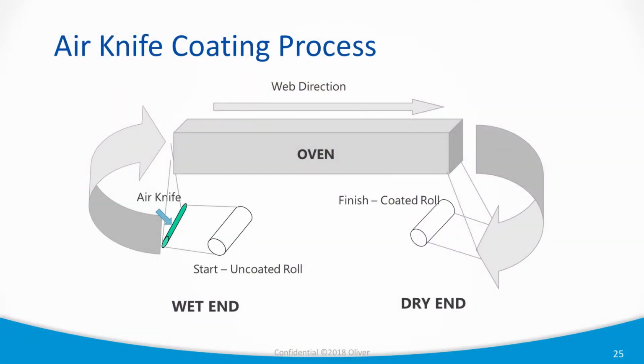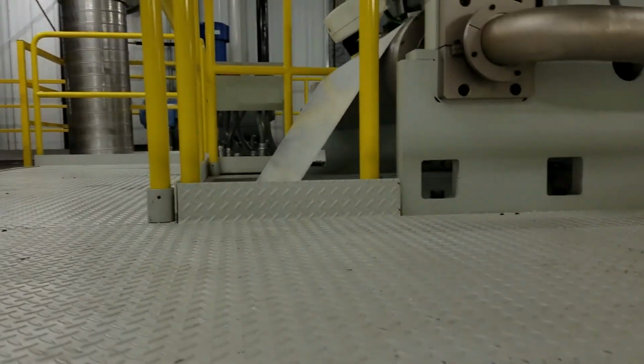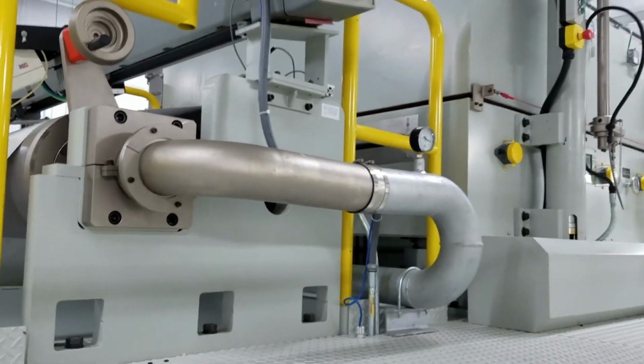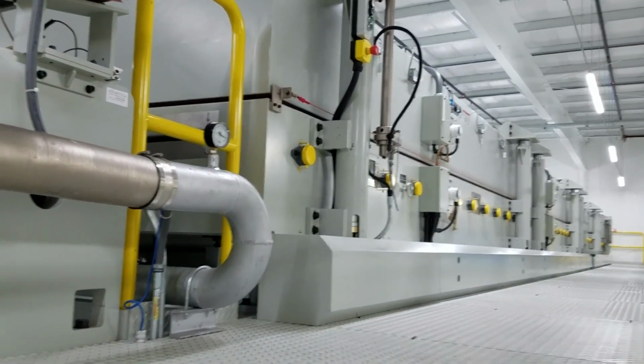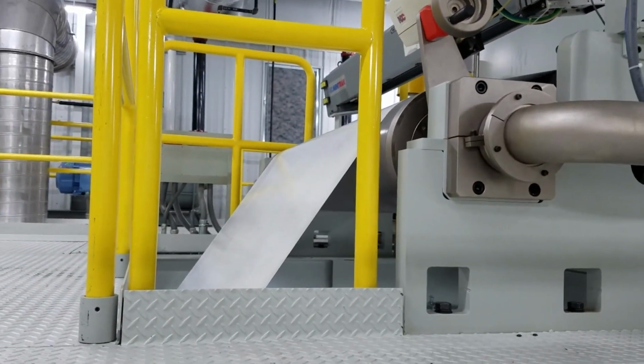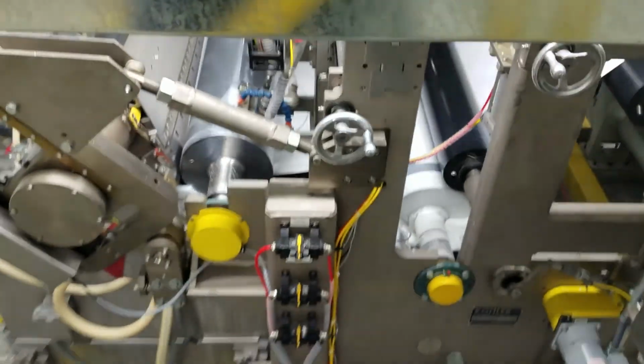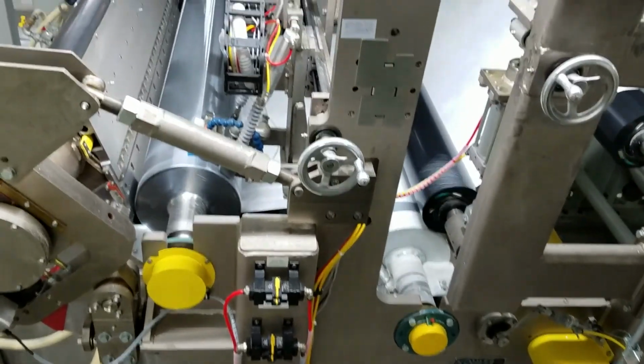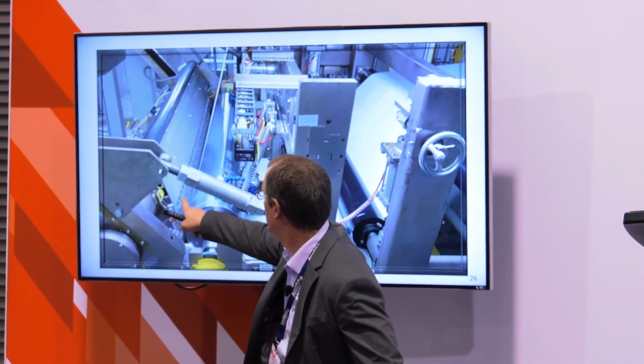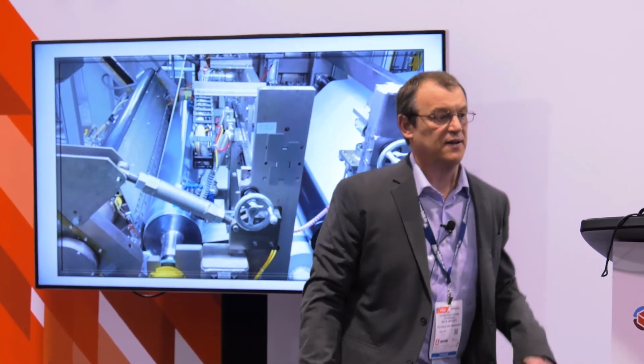And here's another version where you can see the overall process, which is the uncoated roll going through the air knife, and then in this case, of course, different than hot melt, you need to dry off the water. So you need a fairly long oven, you dry off the water, and then you get to the dry end. And here's the picture. You can see the web going up into the oven. So that's after the air knife goes through this long oven. You can see how much oven is needed in order to dry it off. But now we're coming back down, and you can see the air knife is in this area here, blowing off material, and then the web's going up. So that's the basic process for air knife coating.